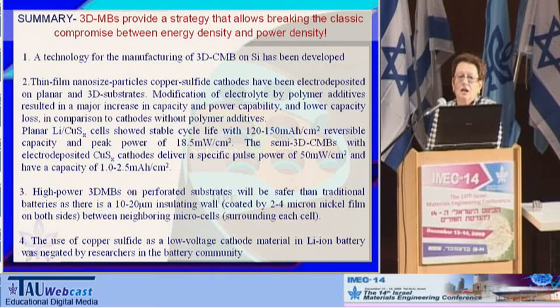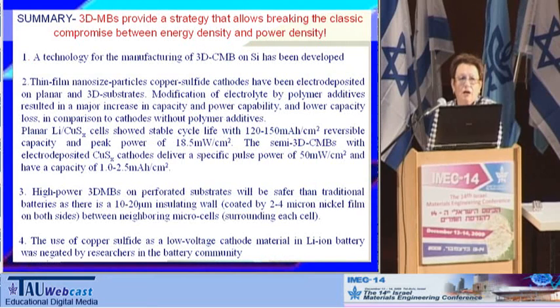These batteries on the perforated substrates will be safer than conventional batteries, and this is due to the small partitions which separate every microbattery unit. And we expect that the optimization of the process will enable us to fabricate microbatteries of the footprint less than 1 square centimeter and even a few square millimeters, which will meet the requirements of microsystems